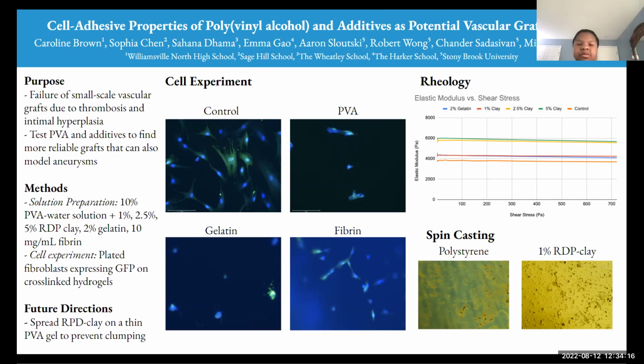We started with the solution preparation. We created a 10% PVA solution in deionized water. We then added our crosslinkers, STMP and NaOH, and divided our solution into samples to test our additives. These additives were 0%, 1%, 2.5%, and 5% RDP clay, 2% gelatin, and 10 mg per milliliter fibrinogen solution. All of our samples were sterilized before we began testing, and the clay was autoclaved.